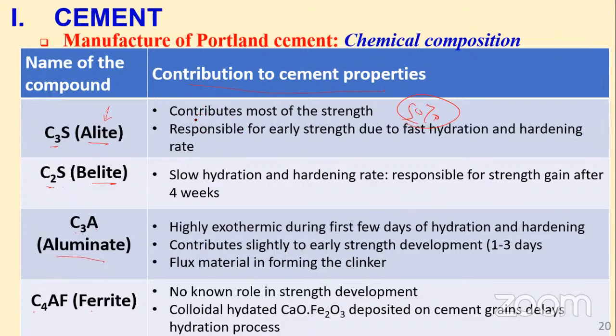Now, this tricalcium silicate is responsible for early strength, especially during the first 28 days. And you're going to see how strength develops. It's not just by becoming hard, you know, it's a chemical reaction that happens when these compounds come into contact with water. Hydration occurs. So the second compound, which is belite, hydrates very slowly. And therefore, this is responsible for strength gain after 4 weeks, after 28 days.